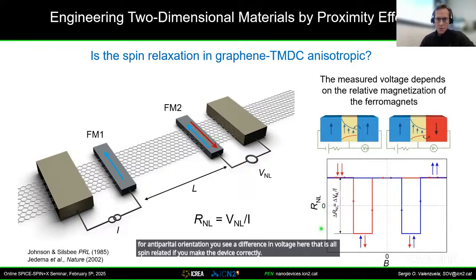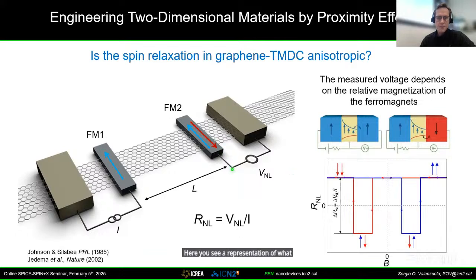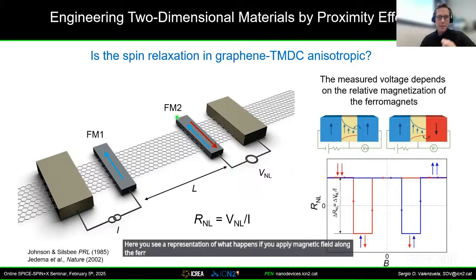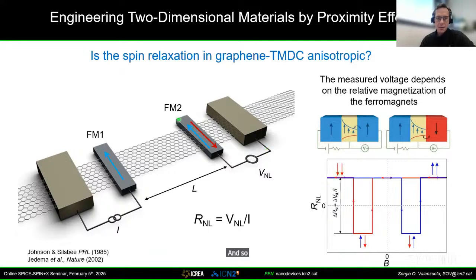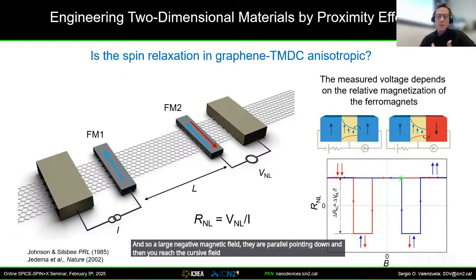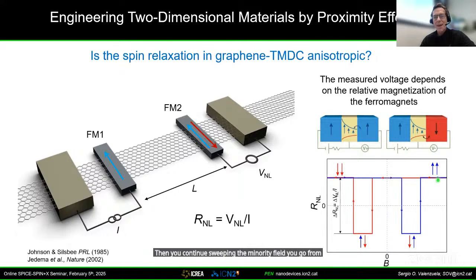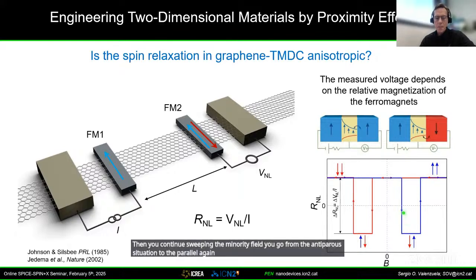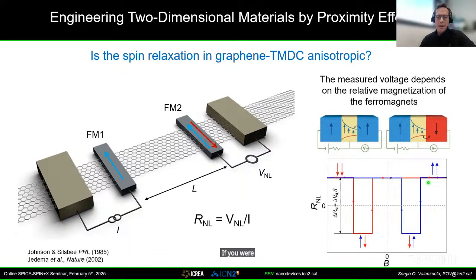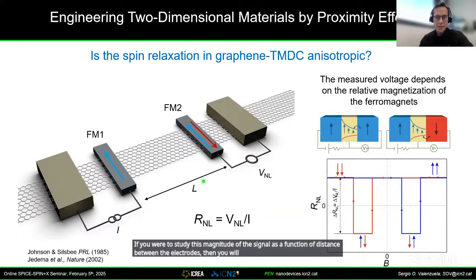So here you see a representation of what happens if you apply a magnetic field along the ferromagnets. The magnetization is typically along the long axis, in plane. This is for shape anisotropy. So at a large negative magnetic field, they are parallel, pointing down. And then you reach the coercive field of the first electrode, which is designed to have a lower coercive field. It switches. Then you continue sweeping the magnetic field, you go from the anti-parallel situation to the parallel again, and then you see this jump. If you were to study the magnitude of this signal as a function of distance between the electrodes, then you will be able to determine the spin relaxation length.